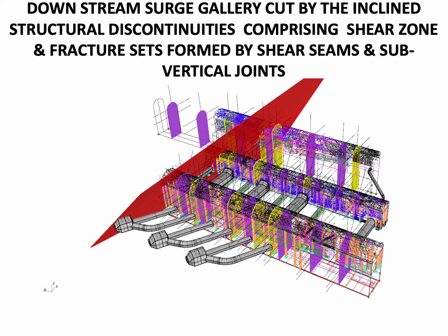This diagram shows downstream surge gallery cut by the inclined structural discontinuities comprising shear zone and fracture sets formed by the shear seams and subvertical and vertical joints and horizontal foliation. This red colored plane represents the shear zone, which is sharply dipping at an angle of 50 to 65 degree and is north 30 degree east in its orientation. The excavation was started from south end of the downstream surge gallery, and at RD 124 to 140, this shear zone was met in the crown, and then it was found to be cutting throughout the depth of the walls. This shear zone also did touch the transformer hall at its gable end, and the powerhouse also just merely touched at its gable end.